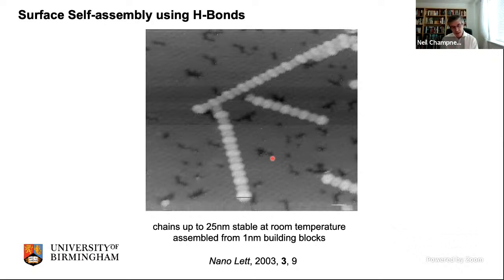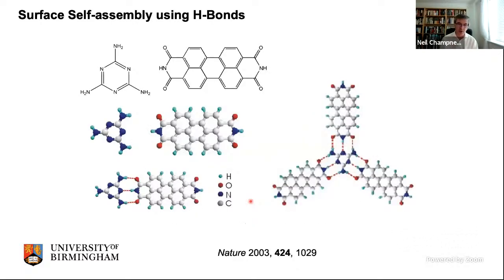So we can see that, and this was interesting to us because it was just the same as the crystal structure. We thought, well, okay, we can use our knowledge from crystal engineering to design structures on surfaces. So this is a one-dimensional system. Surfaces are all about two-dimensional systems. So we learned from the Whitesides chemistry, and we take this slightly longer molecule, which is for geometric purposes, and melamine. And melamine should form a triple hydrogen bond to the ends, these imide ends of this molecule.